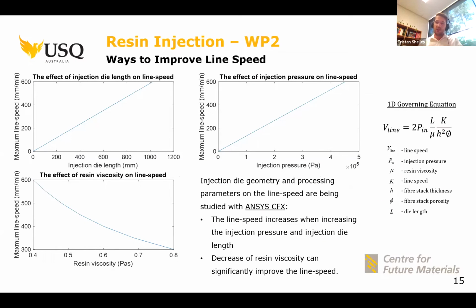So some ways that we've already identified to improve line speed, one of those is simply increasing the die length. That may not be an option for some manufacturers, because increasing the die length means that you need a much larger envelope within which to mount your equipment, your dies, and it can also mean that your die is closer to the pullers, and you may not have enough time without means of direct cooling for the product to cool before it gets to the pullers. But all things that can be worked around.